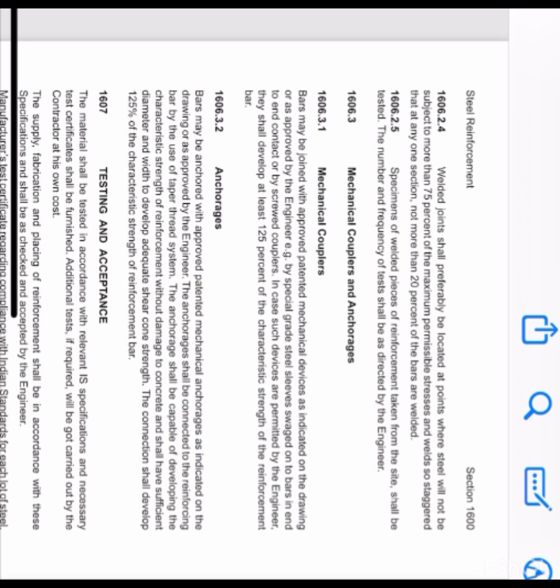Welded joints shall preferably be located at points where steel will not be subject to more than 75% of the maximum permissible stress, and welds are so staggered that at any one section, not more than 20% of the bars are welded. Specimens of welded pieces of reinforcement taken from the site shall be tested. The number and frequency of tests shall be as directed by the engineer.